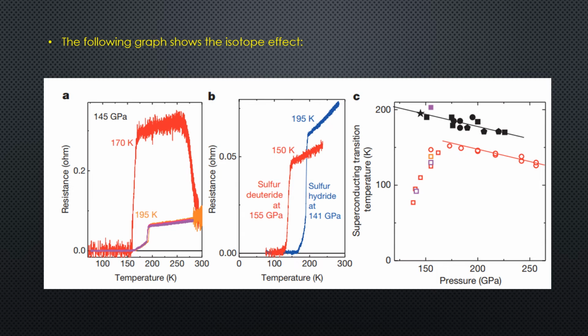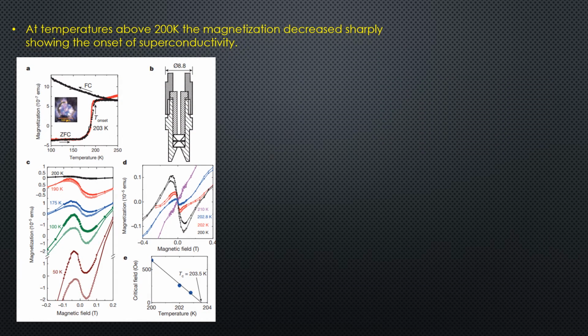The following graph shows the isotope effect. You can see here in the middle graph sulfur deuteride having a lower Tc than sulfur hydride at nearly the same pressures. At temperatures above 200 K, the magnetization decreased sharply, showing the onset of superconductivity. To be exact, the onset of superconductivity was observed at about 203.5 Kelvin, as you might be able to observe from this graph.